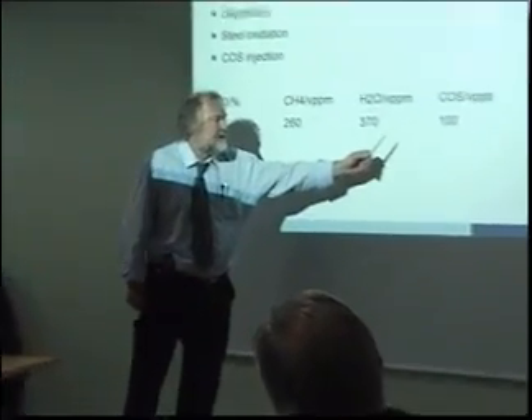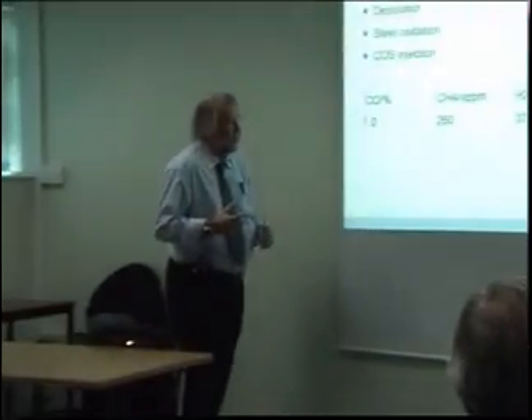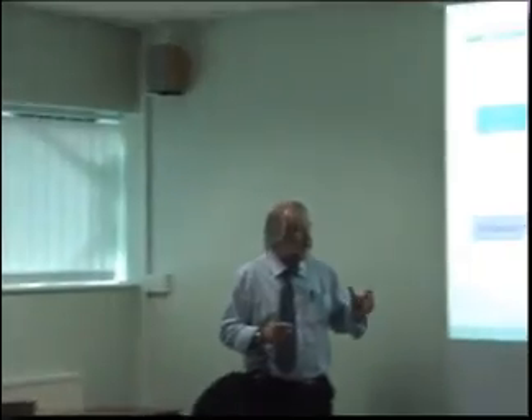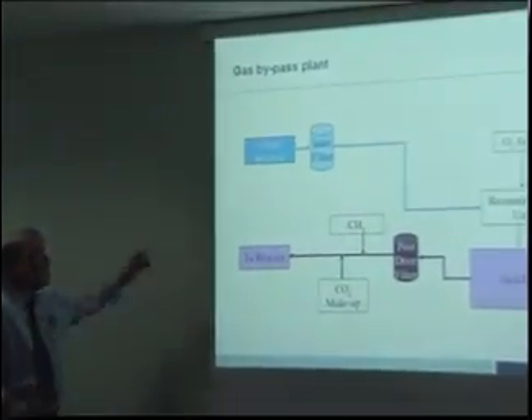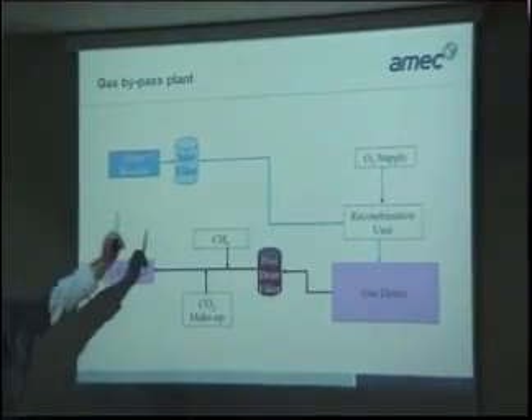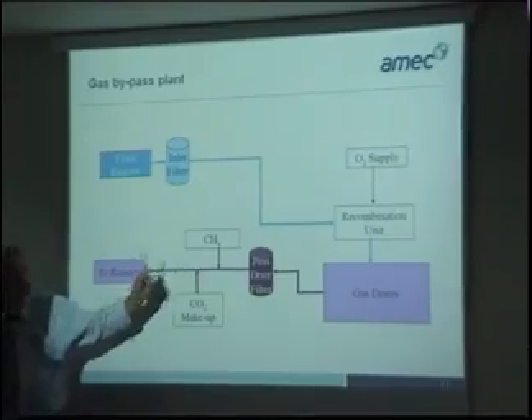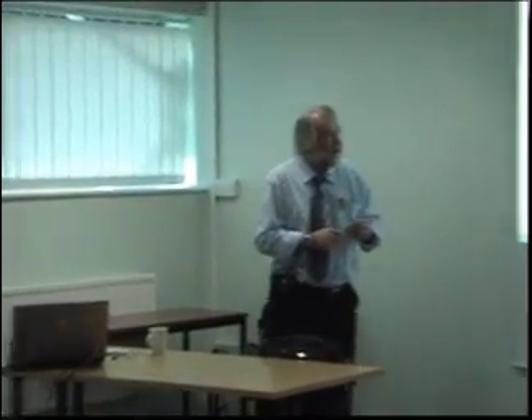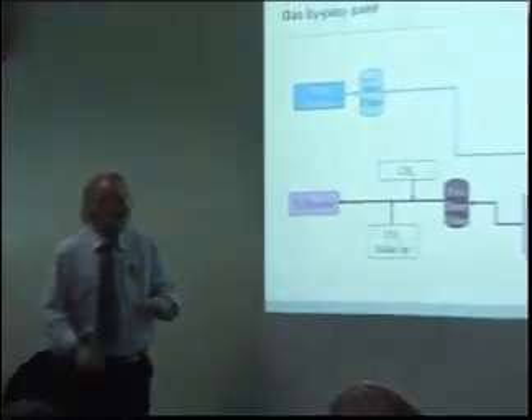And the carbonyl sulfide is added to mitigate carbon deposition. So the bypass plant, there's a small bleed from the reactor. I mentioned 4 tons a second circulating. I think this is something like 20 kilos a second, so it's a fairly small flow, and it's filtered and put through a recombination unit. The recombination unit is basically a platinum catalyst on alumina, and it's there to remove any excess carbon monoxide that's formed. I mentioned earlier the continuous formation of carbon monoxide, and obviously oxygen is needed to inject into the unit to form CO2.